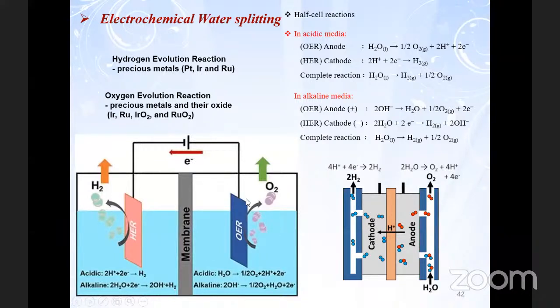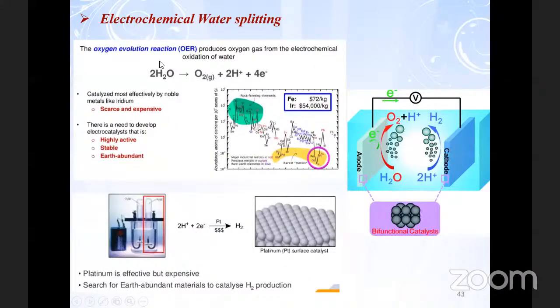The OER catalyst should be highly active, and the reaction should be fast enough so that it provides more H plus ions, and then the hydrogen can be easily produced. But the problem is this catalyst. If you compare the price of iron with iridium, you can see that iron, an abundant material, is only $72 per kg, whereas iridium is $54,000 per kg. This is about the oxygen. Similarly, for the hydrogen evolution reaction, platinum is a very effective, very good material, but the problem is it is expensive.